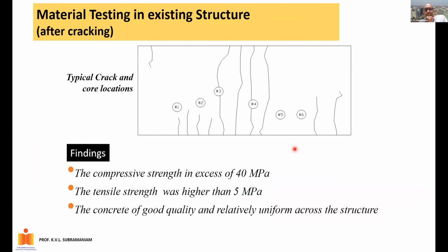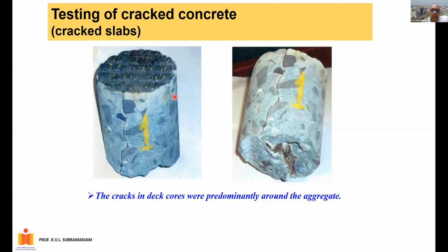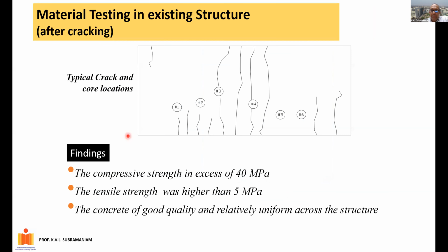This was not cracking that was coming from structural reasons. The compressive strength that we got from cores was also quite high. The tensile strength was high. The concrete was also of uniform quality. Then it was established that when we took the core through the cracked area, so if you go up here, this is a core that was taken through the crack. So there's a core right through the crack.